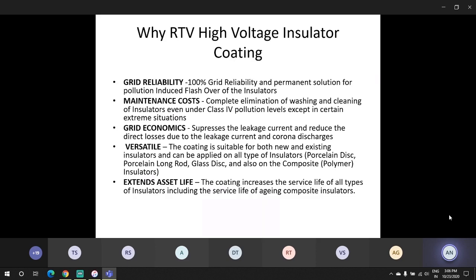Why is RTV silicon high voltage insulator coating recommended? Because it provides you 100% grid reliability. The maintenance costs are completely reduced. It completely eliminates washing and cleaning even under class 4 insulation pollution levels. It suppresses the leakage current. It also reduces the direct losses due to leakage current and corona discharges. It is versatile. It can be used on both new and existing insulators, and on all types of insulators. We do have a case history of even applying it on aged composite polymer insulators. It extends the asset life, which has been compromised due to ever-increasing pollution.